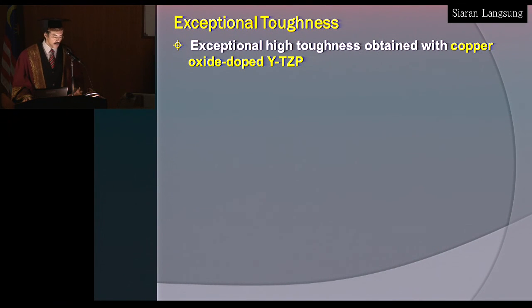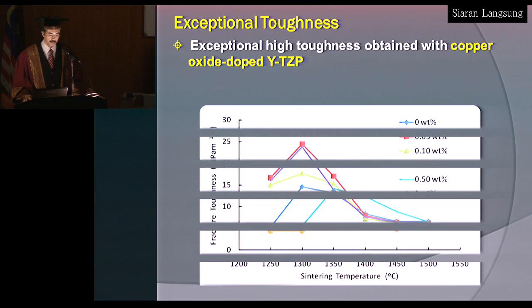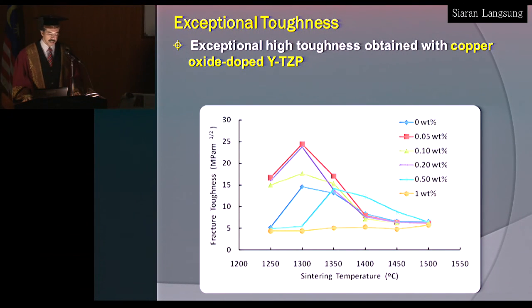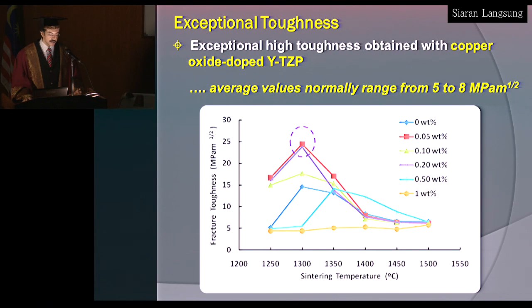And what we found through the research is that we are able to enhance the mechanical properties. Exceptionally high toughness was obtained with copper oxide doping. If you look at this diagram, the values there show that values in excess of 20 megapascal meter to the power half are possible with copper-doped zirconia. Normally, zirconia would exhibit values in the range of 5 to 8 megapascal meter to the power half.